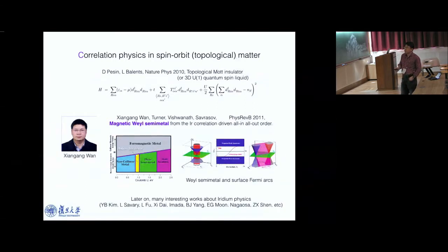So they found that the band structure of the conduction electrons of the iridium 5d electrons has been reconstructed by the presence of magnetic order. So they find that at the Fermi level there is this point band touching. So this valence band and conduction band touch at discrete points, and these discrete momentum points are called Weyl points. And these Weyl points come in pairs with plus or minus chirality associated with the Weyl nodes. And the most important result in this paper is the theoretical observation of the Fermi arc surface state connecting the projections of the Weyl nodes of different chirality onto the surface of a chunk of material. So this is the non-trivial surface-bulk correspondence. That was emphasized and pointed out in this great paper.